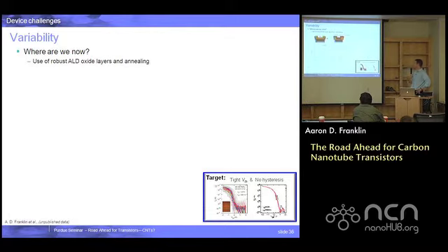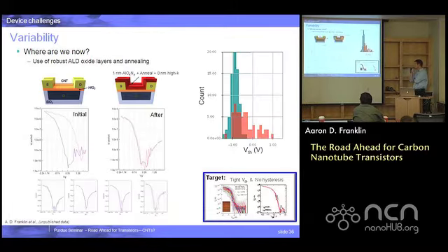So where are we now? This is some very new data that uses more robust layers that were ALD oxide deposited. If you're curious about these layers, I'm happy to talk about them at greater length offline. I'll talk about this one again in a moment. But the hysteresis suppression is really near perfect. The devices, if they have hysteresis, it is very small in any of the ones with this passivation technique. And the threshold voltage distribution is tightened very well. The red is before and the blue is after.